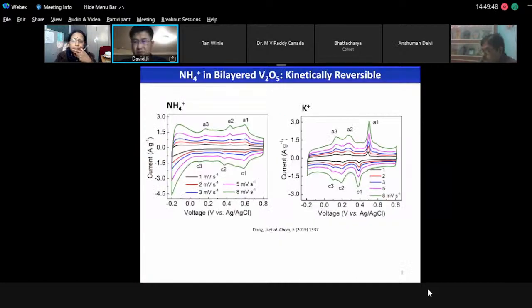So something interesting going on afterwards, and we found, ammonium ion. Ammonium is different from potassium. Ammonium is molecular, is non-metal. It has a lot of protons. So if you have protons, what about hydrogen bonding? It's not going to be pure ionic bonding anymore, because if we insert ammonium into metal oxide, the space is so crowded that the hydrogen atoms of ammonium will have no other choice but to interact with oxygen atoms of metal oxide. When they interact, because they are so close, they have to form extremely strong hydrogen bonding. So that's the hypothesis, and we hope to see some kind of flavors derived from the hydrogen bonding.